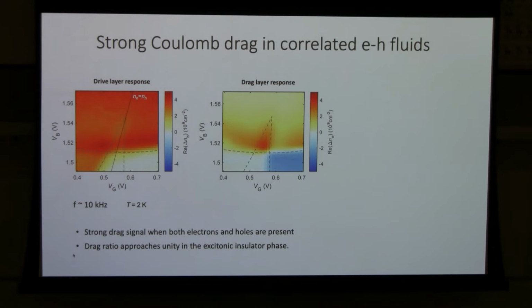This part shows the electron current, and we actually see very different behavior. If you look at the low bias voltage, you have hole doping here, but in this region you have only electron doping. In that case, when you modulate the gate voltage, you find that the electron density change has the opposite sign compared with the hole density change, because they have opposite charge. If you apply positive gate voltage, you will repel holes but attract electrons. So the electron density change and hole density change have opposite sign.